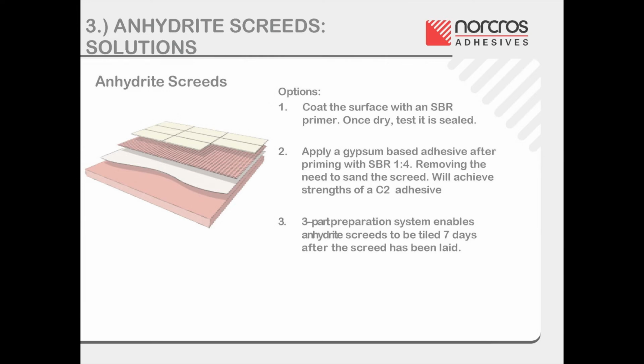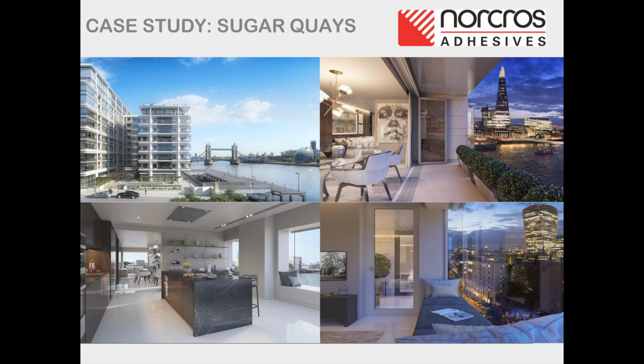Fast track method. A 3-part preparation system is now available which enables an anhydrite screed to be levelled or tiled using a cement-based adhesive after a minimum of 7 days or a maximum 95% relative humidity. This means that the drying time for a 40 mm screed is reduced by at least 32 days and a 60 mm thick screed by at least 72 days, providing cost savings on the build.